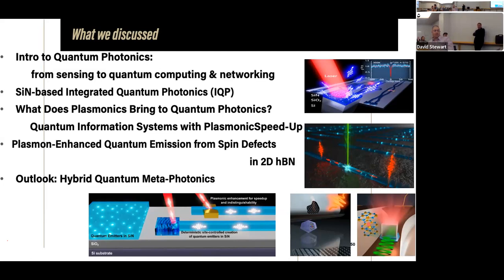And I guess one of the main messages in my presentation, there are two ways to increase this coupling. Use dielectric cavities or plasmonic cavities. If it's dielectric, it's still diffraction limited. And then, yes, we are talking about structures like 200 nanometers. Why 200? Because, let's say, if it's silicon, refractive index 3.5, let's say 1.5 divided by 2 times 3.5, that gives you 200 nanometers. So several hundred nanometers, relatively large. First of all, it's still not that big, but relatively large.